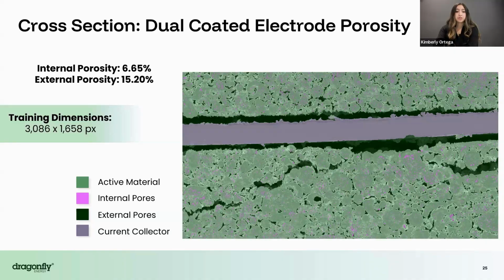Additionally, this method introduces some sample preparation artifacts that can skew our porosity results. In this image, you can see delamination on both sides of the current collector. This is likely caused by the physical cutting of the electrode, which then inaccurately increases the measured external porosity. So without 3D validation, we might misinterpret these artifacts as real structural defects in the electrode, and while cross-sections are fast and informative, they're best when paired with 3D methods.